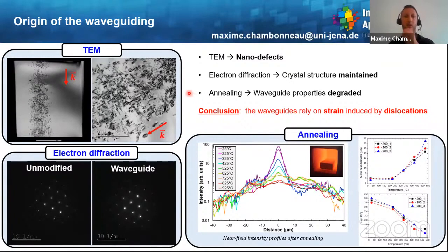So finally, we have carried out recently some annealing experiments, as you can see here. I will not go into the detail, but the main conclusions of those experiments are, when you increase the annealing temperature, the waveguide's properties are degraded, namely the mode field diameter increases, as you can see here on the right, and the refractive index change decreases. So our conclusion is that the waveguides we have written rely on strain induced by dislocations.